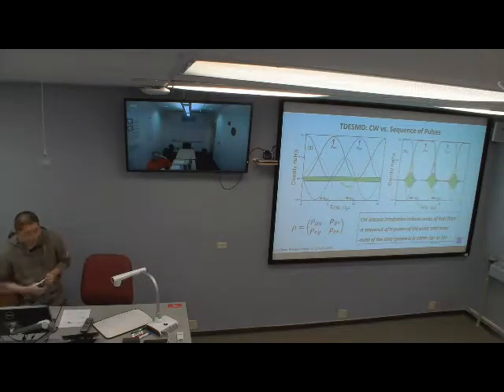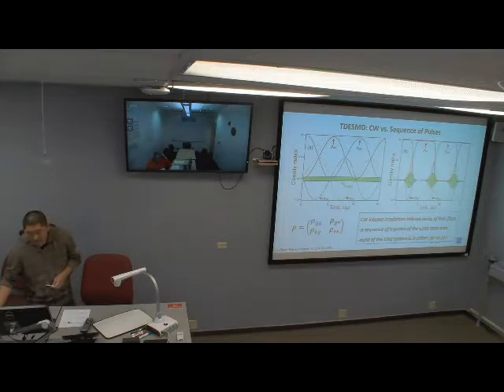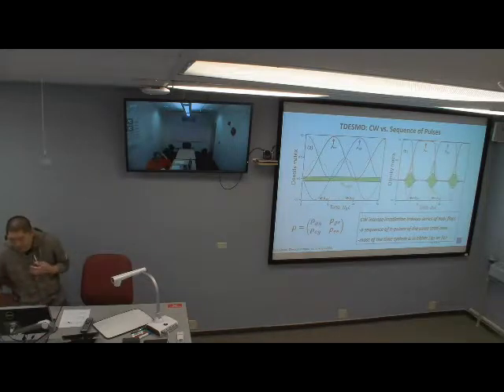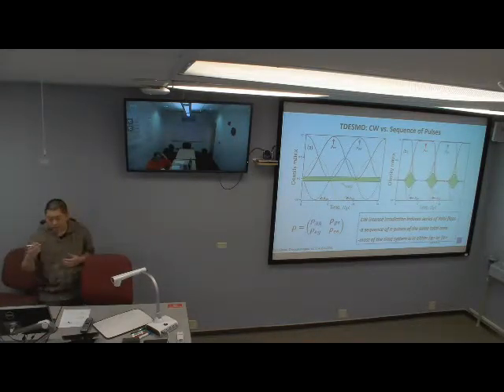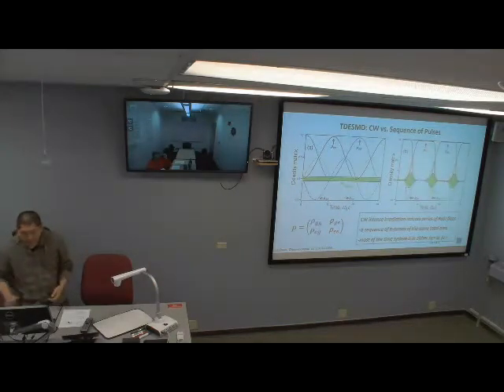So here, the first panel shows an evolution of a density matrix induced by continuous wave excitation. The blue and the red represent the diagonal elements of the density matrix, while the yellow and purple represent the off-diagonal elements of the density matrix. So that's a little bit complicated. So we want to make a continuous transition from CW excitation to a sequence of pi pulses. So as we can see in panel B, the average pulse area per time interval is kept the same as in panel A. The occupation of the ground state swaps from 1 to 0, and the occupation of the excited state swaps from 0 to 1.